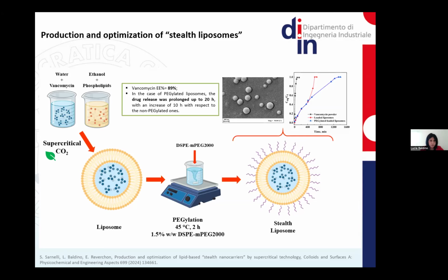We use this kind of PEG, that is the most frequently proposed in the literature for this application, and we optimize this step in terms of concentration of PEG and temperature, duration, and mixing speed of the pegylation step. And here you can see the optimized parameters obtained from this step. And stealth liposomes were characterized in terms of morphology. As you can see from this scanning electron microscopy image, we obtain liposomes